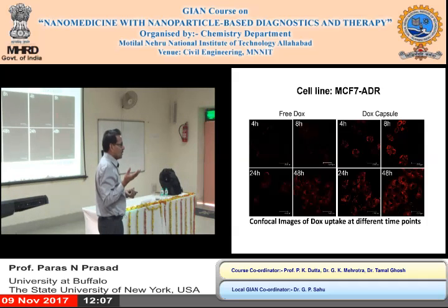Standard chemical techniques. First is elemental, right? But that may not be specific enough because your nanoparticles may have functional group too. So the second one is spectroscopy, right? You can do IR spectrum, look at vibrational bands of this and see whether the dye is in there, okay? Your drug is in there. Your drug has certain vibrational IR spectrum, fingerprint, right? Or you can do UV visible to look at whether absorption band, electronic absorption band of the drug is there or not, right?